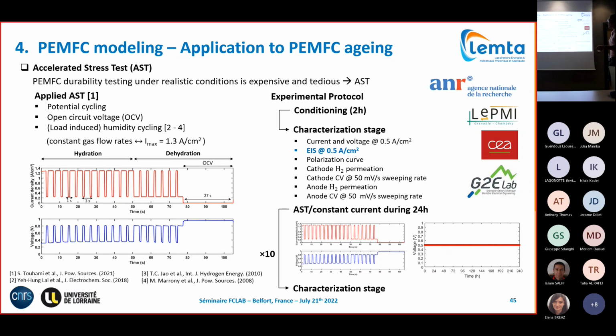independent duration of high current and low current operation, which will induce more hydrated periods and dehydrated periods. And this will probably create mechanical stress of the membrane due to swelling and shrinkage from dehydration. So in this procedure we apply, one period is 105 seconds, and we apply this repetition of the cycle during 24 hours, and after the 24 hours we make a stage of characterizations, measuring current and